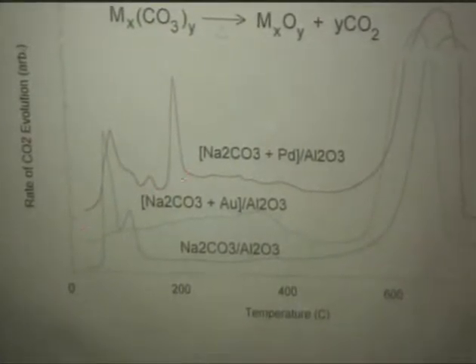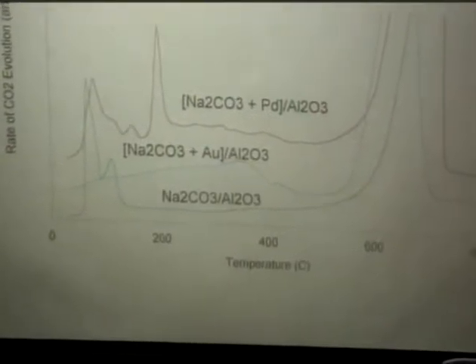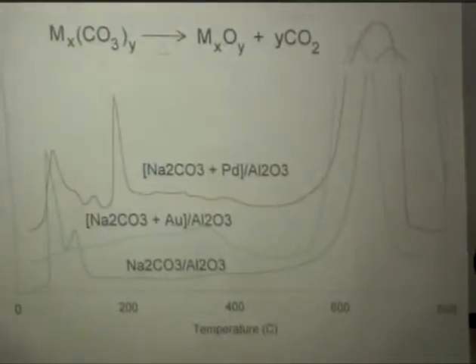When gold is present, we see a structure in here, a very broad diffuse decomposition of that gold carbonate. But we were very interested that when we looked at the palladium species, we saw a very sharp decomposition here at just about 200 degrees exactly, and then a more diffuse decomposition. And again, in all these you see that we have excess carbonate present. So it looks like, yes, we've seen with titrations, we've seen with infrared, and we've seen now with simple decomposition that it sure looks like we're making some type of metal carbonate as a precursor to this catalyst. What we thought was interesting is what would happen if we just focus on that sharp decomposition. That was an interesting species for us.